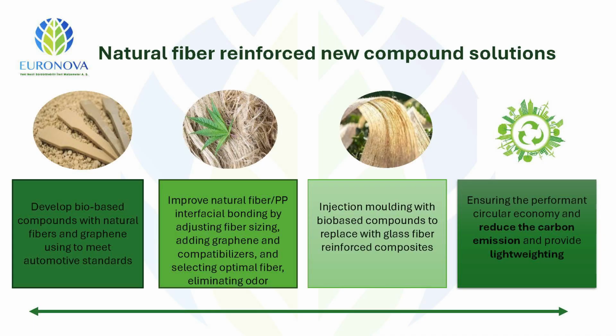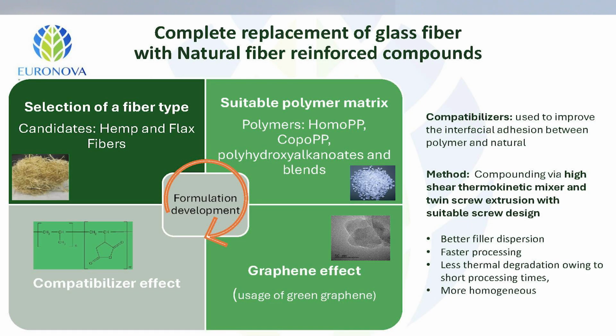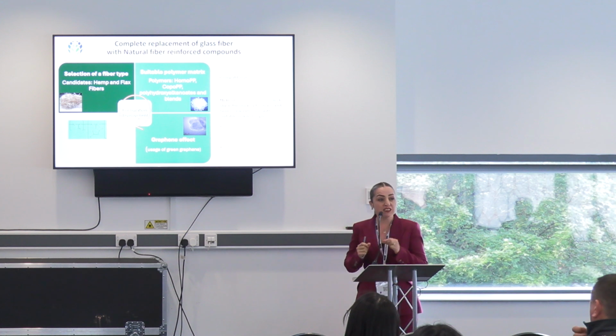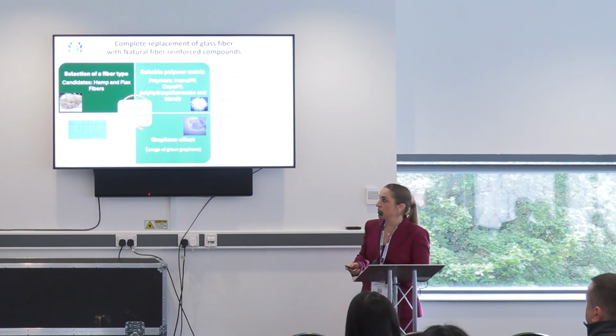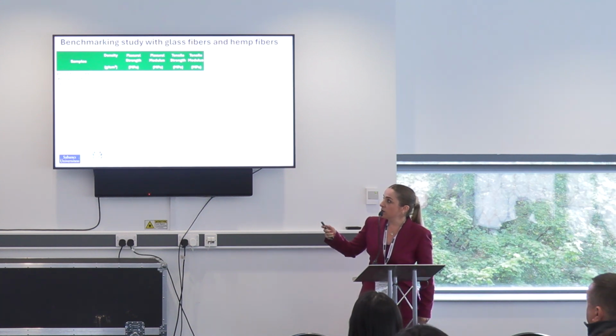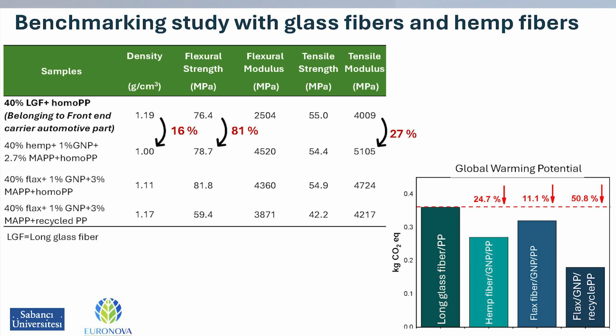And also we would like to push people to use natural fibers. Yes, there are specific examples, and the problem with natural fibers is the odor and also the sizing problem. Here again, graphene can be a good solution, eliminating the odor problem and acting as a good compatibilizing agent within the selected matrix. Then in this matrix, we are formulating with hemp fibers, flax fibers, or other fiber forms in chop form, but not in continuous form. In chop form, you can use these materials instead of long glass fiber. I would like to show one example. For example, at the top, you can see 40% long glass fiber with homo PP polymer, which is under serial production for Renault parts.